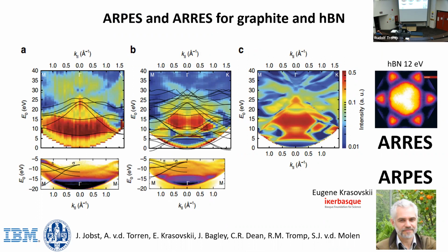Reflected electrons, and in the same microscope on the same sample, we can do angle resolved photoemission and look at the unoccupied bands. The little piece that we miss here, about 5 eV, is between the top of the valence band and the vacuum level. There's a region that we can't access experimentally.